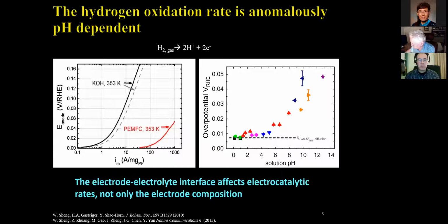So I show you one result here where the same catalyst is being used under the same thermodynamic driving potential. So this is the same voltage for electrochemists on a reversible hydrogen electrode scale. In other words, we've already compensated for pH. There's the same driving force to reaction, same platinum electrode, but because we ran it in acid, the current is two orders of magnitude higher than if we ran the reaction in base. So that's telling us the electrolyte also affects the catalysis.